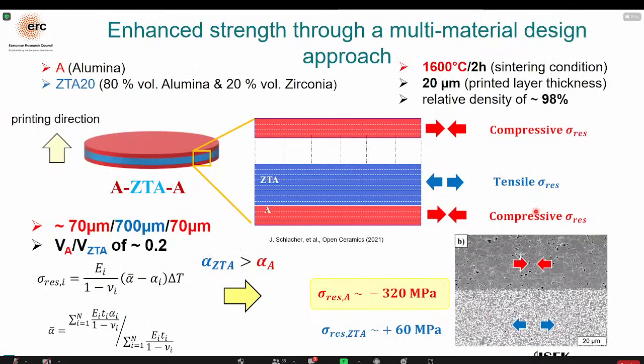So the last thing I would like to show you is a design approach to combine materials, alumina with zirconia-toughened alumina. If we combine ceramics with strong interfaces, we can introduce compressive residual stresses. Depending on the chosen design with our volume ratio of 0.2, which means we need to think about the layer thicknesses.